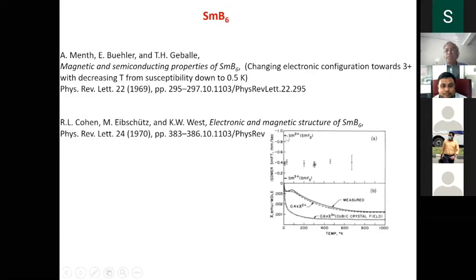If this material is trivalent, you should get an isomer shift close to 0. Divalent, you should get somewhere around -1. In this case, they're getting something in between. Remember that, neither here nor there, somewhere in between. And the susceptibility also is something in between. That's what you expect for divalency and trivalency. Of course, this picture is not very clear. It's from what I explained to you.